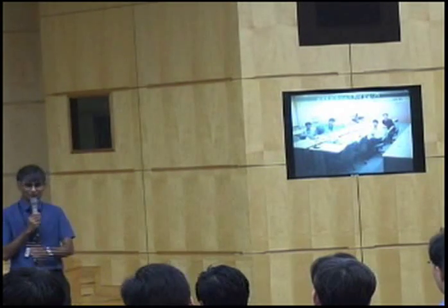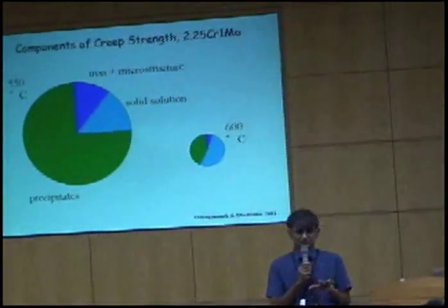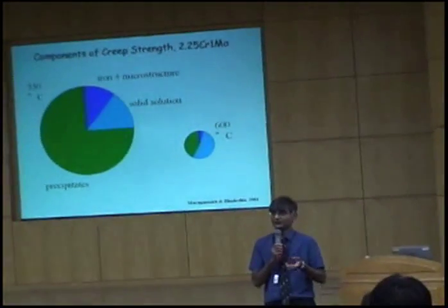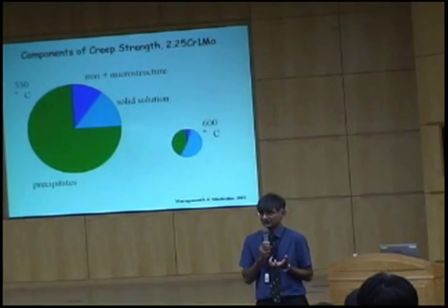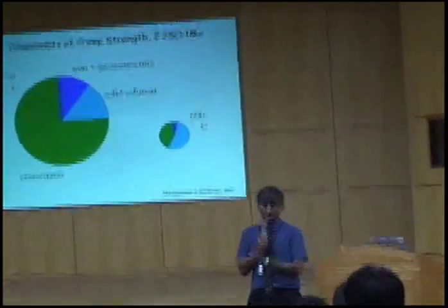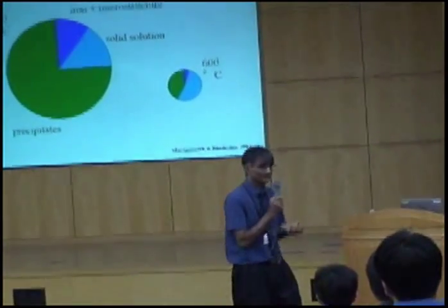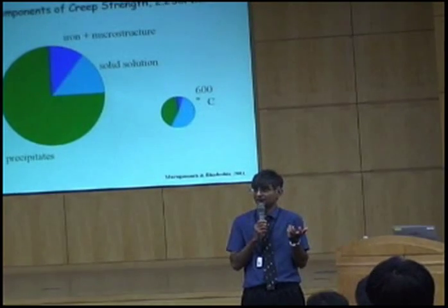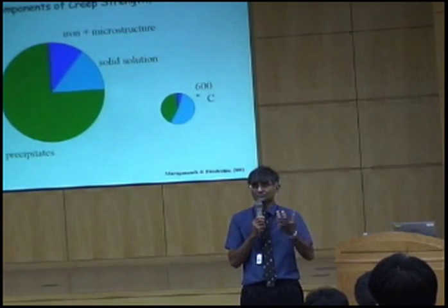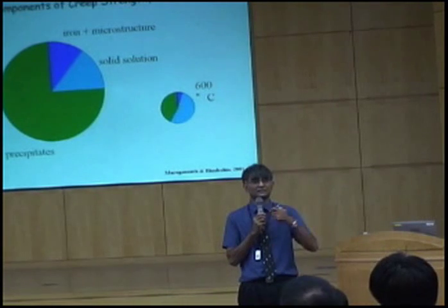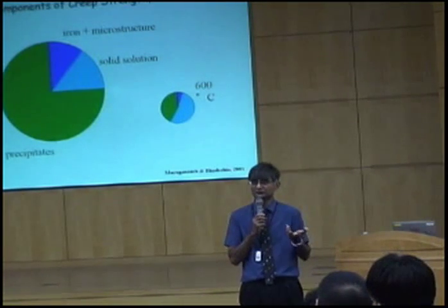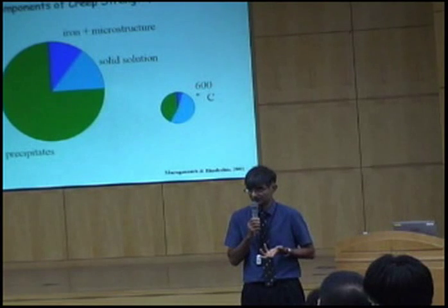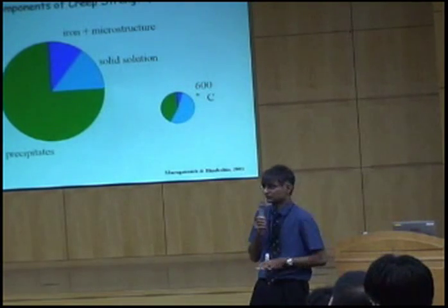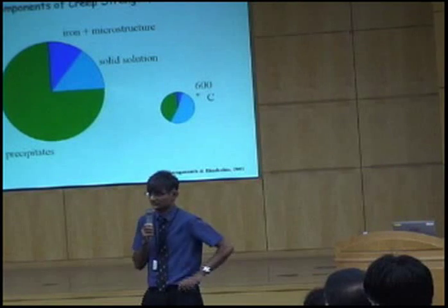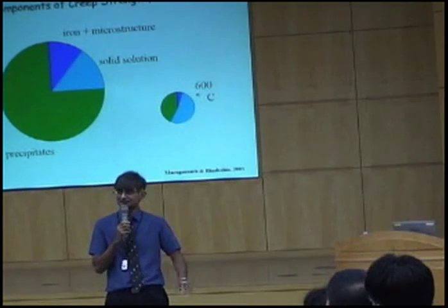Okay, so I was talking about creep rupture strength. Creep rupture strength is very complicated. It depends on so many variables that all the simple metallurgical theories that have been developed for creep simply cannot reproduce the results, so they cannot make predictions. If you ask me what happens if I add 1 weight % of molybdenum to this steel, how will the creep rupture strength increase? You cannot answer that question using all the creep theory that has been researched for more than 60 years.